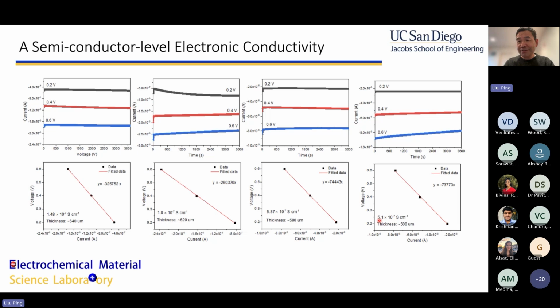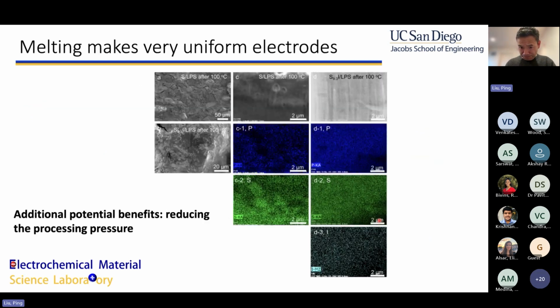If you repeat the calculation I did at the beginning, now if you make a 1 nanometer thick film, you will see you are in business. Now the electron actually can go through a 1 nanometer film without any difficulty. So finally, we have a solid state material that's electronically conducting enough. It's rich in free radicals, and it can be remelted. So the material has the potential to address some of the most difficult problems suffered by elemental sulfur.